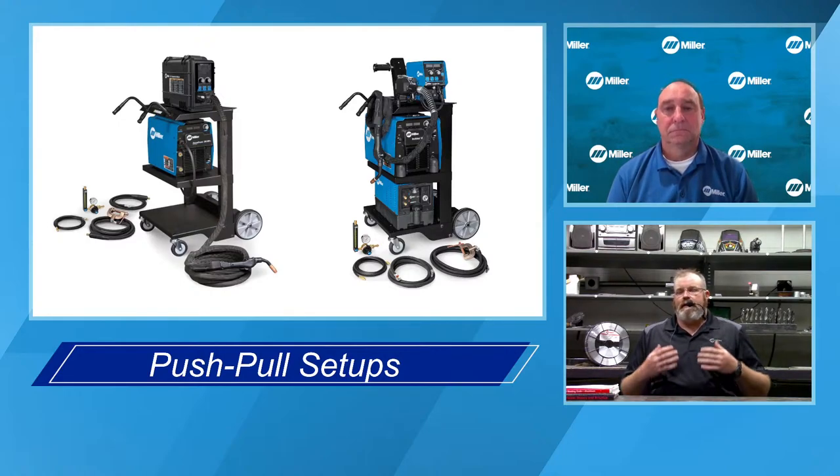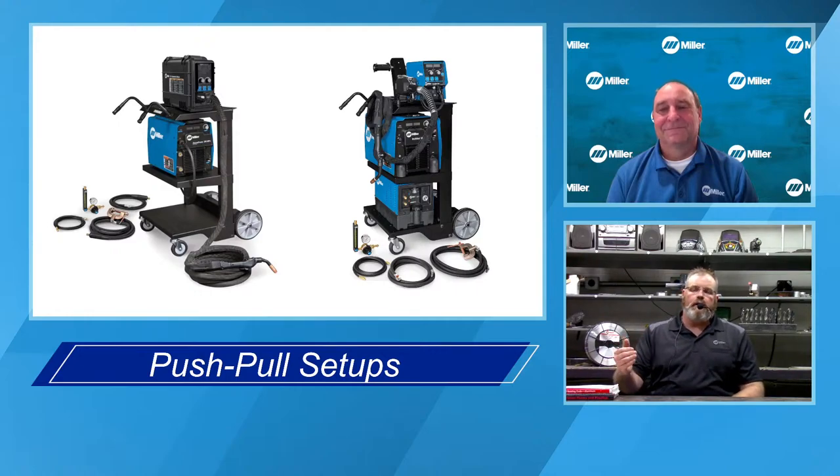When we're dealing with aluminum, and you guys know this, and we've talked about this in other Shop Talk Lives, the feedability of aluminum is very critical. And so we don't want to be pulling on that wire into tension. We don't want to be crumpling it into compression. What's going to happen is that torque motor is just going to help flow that wire down there and just keep it floating down the liner while the front motor pulls the wire out.